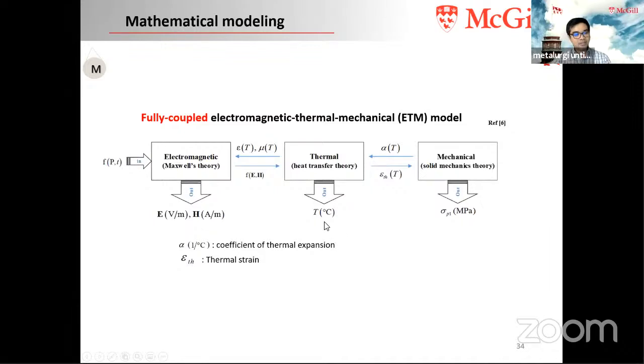For example, the permittivity of the rock at a temperature of 25 degrees Celsius will be different from the permittivity of the rock at 200 degrees Celsius. So that's why it has to be fully coupled between the electromagnetic and the thermal, and then the thermal will expand, creating expansion of the grain boundaries, and it creates cracks. Those cracks will also affect the heat transfer because of the release of the energy. So we model the three-way coupling of wave, thermal, and mechanical systems of our rock microwave.